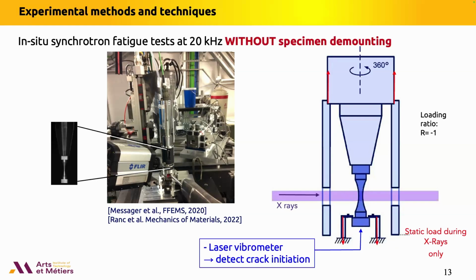And this piezoelectric produces a vibration at 20 kilohertz that is applied here at the top of a horn. This horn amplifies mechanically the vibration, and this vibration is applied at the top of the specimen. So the specimen is here. This system is mounted on the beamline of the synchrotron. And when we do not load the specimen at 20 kilohertz, we need to be able to do the X-ray scan, in order to reconstruct the 3D geometry of the material and of the defects.